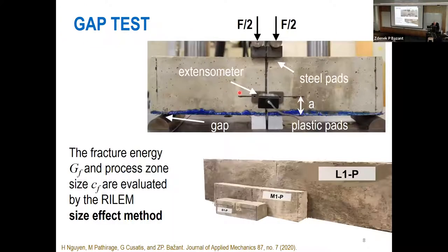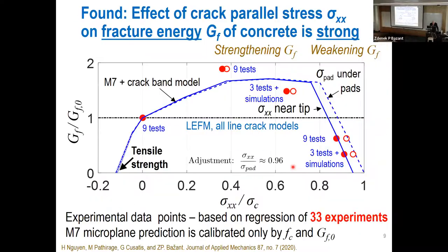I will go quickly because I discussed it already before. This is a picture of the test for concrete. Now we use the size effect to determine the fracture energy and the material length parameter. So this is an example of the specimens for concrete that are tested. And the result of this test I summarize here. We plot fracture energy normalized by the fracture energy at zero normal stress, against the crack-parallel stress, sigma xx.